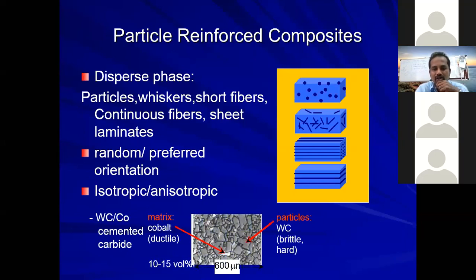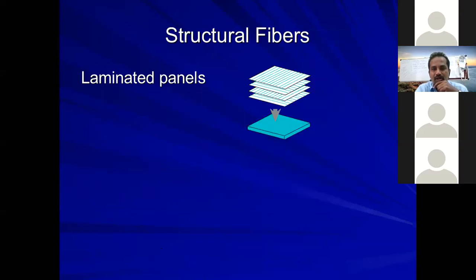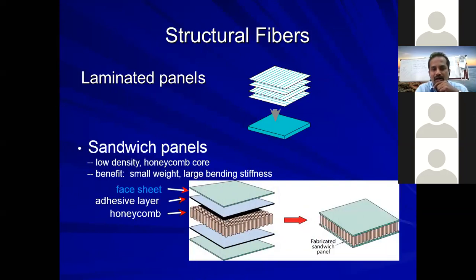Also, tungsten carbide, which is brittle and hard, is reinforced with cobalt, at 10 to 15 volume fraction. See the scanning electron microscope image of the tungsten carbide reinforced composite material. Now the structural laminates: first are laminated panels, sandwich and honeycomb materials. The honeycomb is a copper type honeycomb structure, laminated between two sheets using epoxy as the matrix. This gives large bending stiffness and strength.